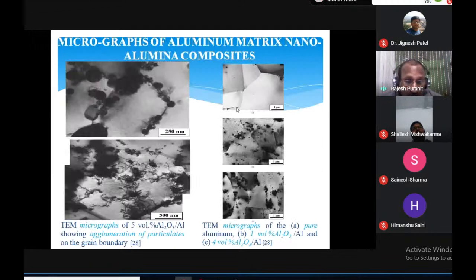These are basically TEM micrographs shown in this figure. First, on the left side, we see the TEM micrograph for 5 volume percent of nano alumina with aluminum, showing agglomeration of the particles on the grain boundary. We are seeing different grains, and on the grain boundary, particles have got agglomerated. The bottom graph is also showing a similar kind of result.